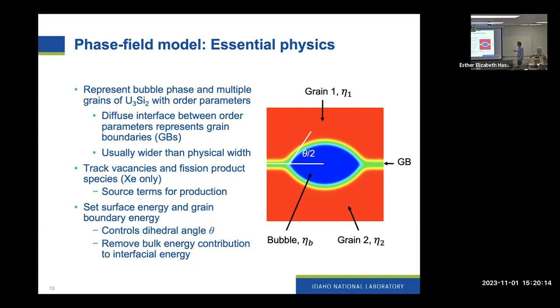And then the grain boundary is represented by a diffuse variation between those order parameters across the interface. And then we have another order parameter for the bubble phase. And again, we have a smooth variation of that order parameter from the bubble into one of the grains. And so this so-called diffuse interface approach usually has grain boundaries that are much wider than the actual physical width of an interface, for reasons of computational efficiency. So that's the basic idea.